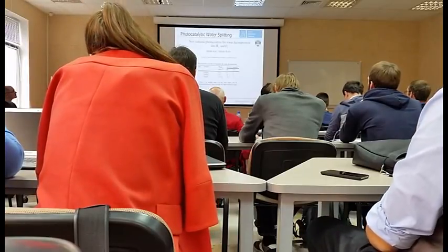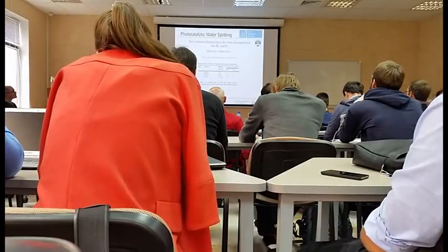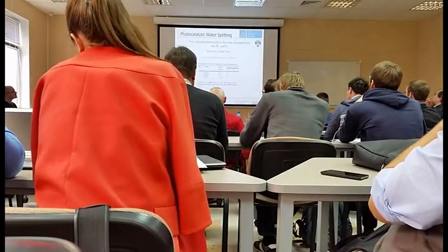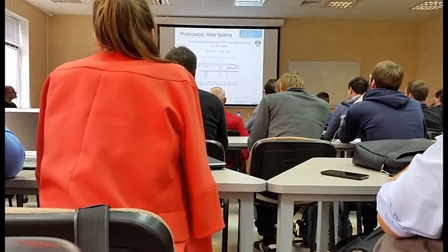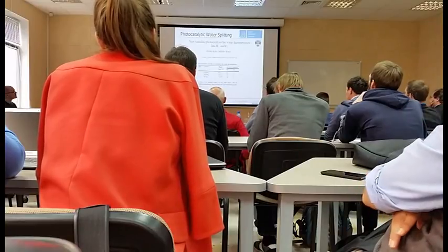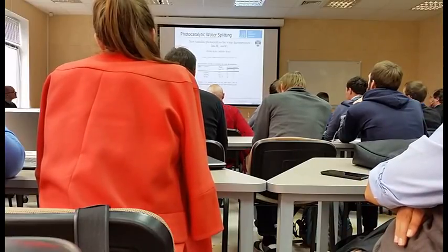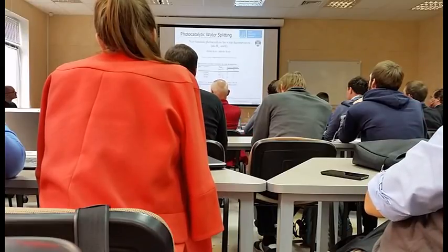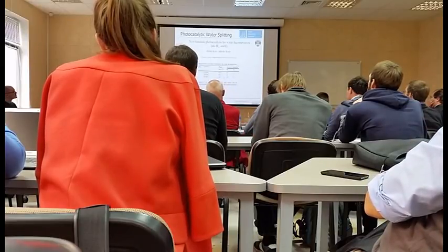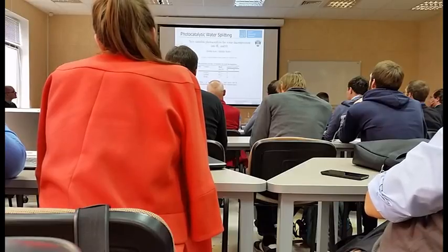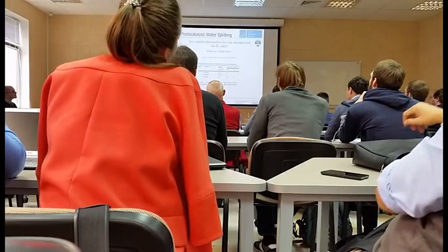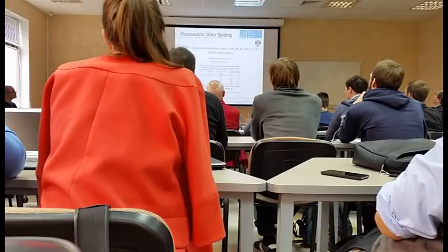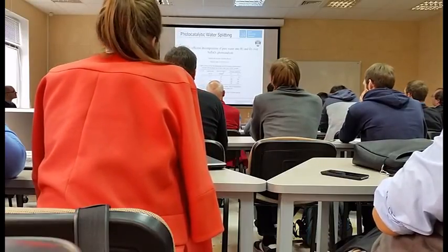But as you see here, most of these materials have very wide band gaps, so they are nice for the laboratory where you have UV lamps. But even if we depleted our ozone layer completely on the Earth, we still wouldn't have enough UV light of, let's say, 4.7 electron volts available, so we definitely need other materials for visible light applications.